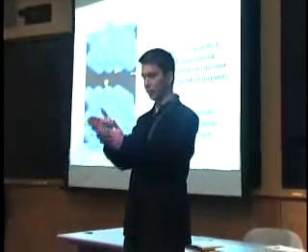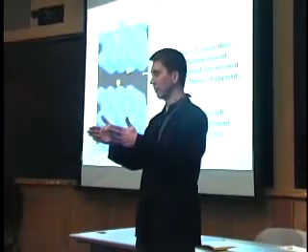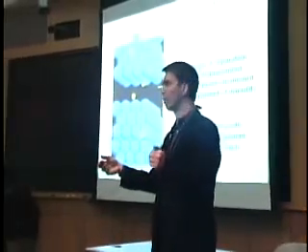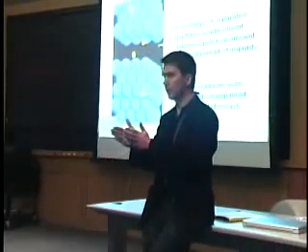You could make a slab. You would define a plane where you open up the slab and you remove the two slabs farther and farther apart. So it's like you're opening a crack. You keep track of the energy, and the derivative of that is, of course, the force required to separate the slab. But think of the problem now if you want to do that with an impurity. You have to now equilibrate the impurity at every separation of the slab.